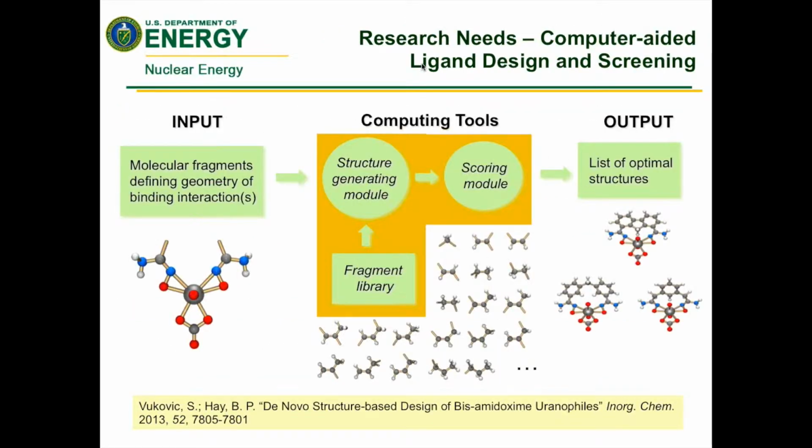And then the other example I gave here is the kinetics and thermodynamics. In this case, you can see we use the enthalpy study to suggest the overall complexation is an endothermic process. That means if you increase the temperature, the reaction will favor the product. In this case, if we increase the seawater temperature, we expect to see a higher adsorption capacity. So that's what we validate through fundamental understanding to the field study. So we correlate that relationship. So I also give a couple references down there too.